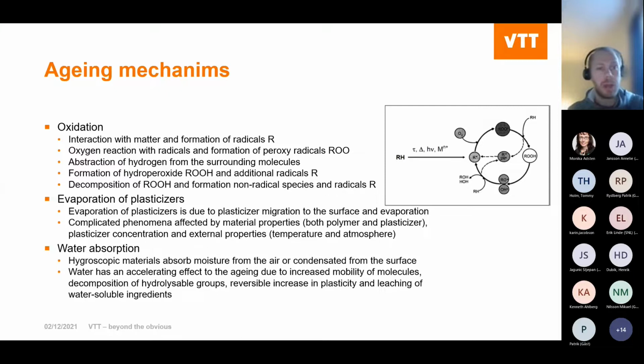Then about the aging mechanisms, we have identified so far three which the joint sealants are facing. First is oxidation. This is due to the interaction of matter with either thermal movement or radiation, which causes the formation of radicals in the material. These radicals further react with oxygen, forming peroxide radicals, and these peroxide radicals can abstract hydrogen atoms from the surrounding molecules, which causes formation of hydroperoxide and then further more radicals. The decomposition of this hydroperoxide can cause either non-radical or radical species.